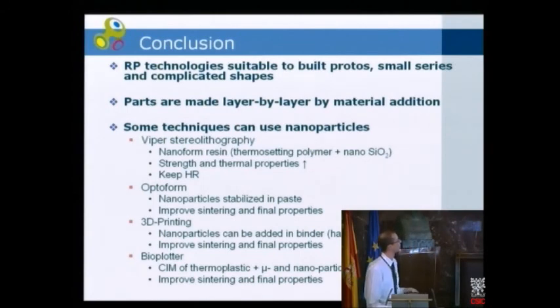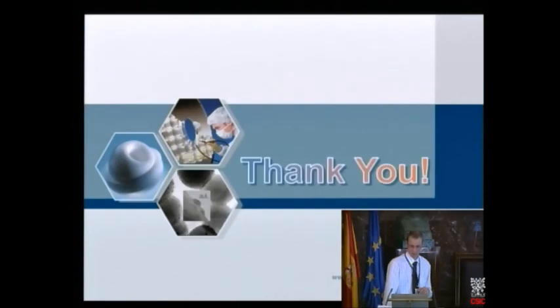In 3D printing, we can add nanoparticles inside the binder instead of inside the powder, because it's too hazardous because of the volatility of nanoparticles. They are not in a stable state inside the powder because they are exposed to the atmosphere. And finally, by using bioplotter, we can do ceramic injection molding of thermoplastics loaded with nanoparticles or microparticles, and this will lead to improved sintering and final properties too. So, thank you very much for your attention.